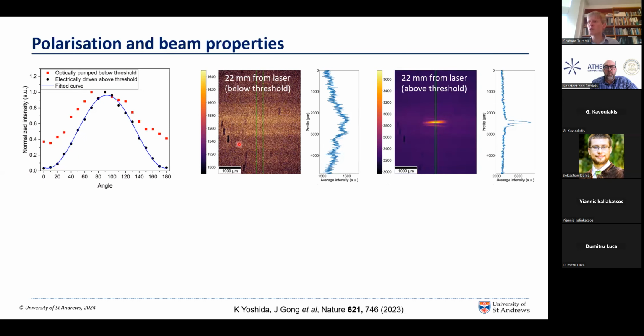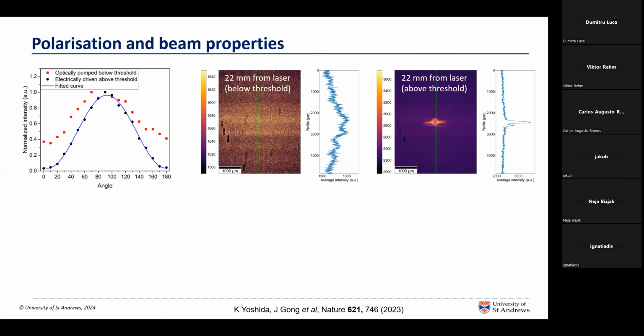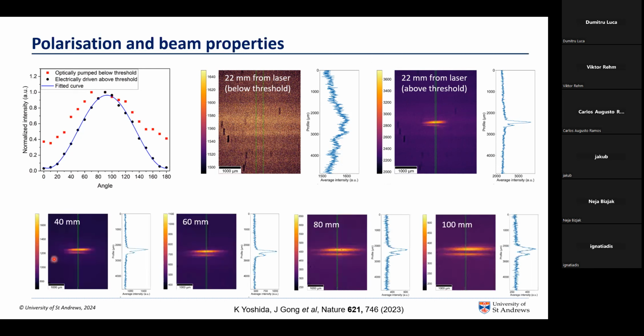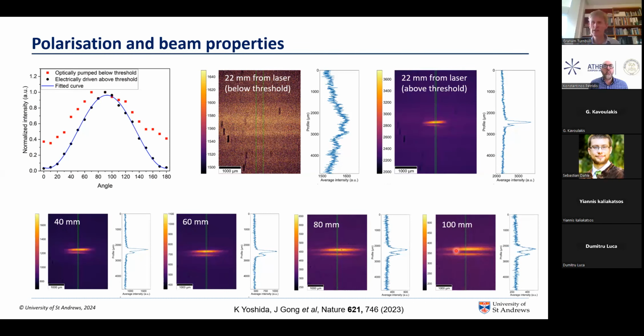We also see that this shows the beam emitted onto a camera at about 2 centimeters from the laser. Below threshold, we have some structure that comes from the grating embedded in the waveguide. Above threshold, it comes down to this small, narrow beam of light being emitted. This double-lobed pattern of the beam is characteristic again of a surface-emitting DFB laser. As we move the camera progressively further away from the laser, we see this well-defined beam that's gradually diverging in the direction perpendicular to the grating grooves and diverging a little bit more along the grating grooves, again typical of the resonator structure that we are using. So we've got a nice, well-defined laser beam and all the characteristics of a laser.